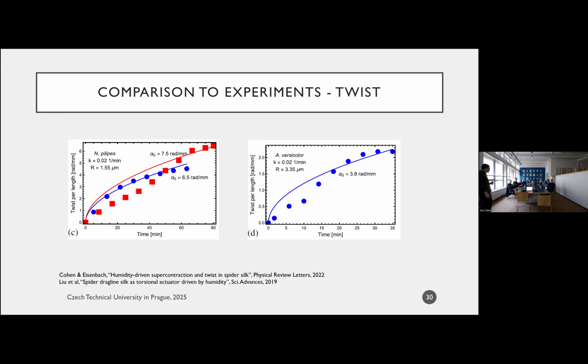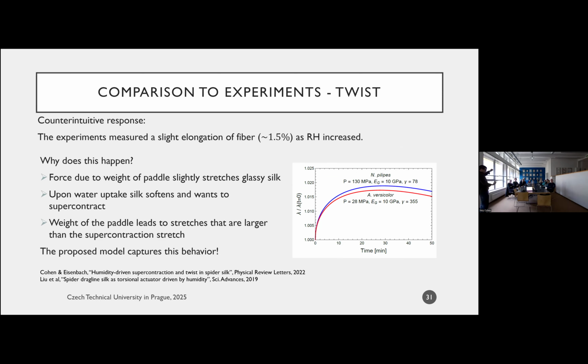And then the reviewer asked us, he said, in the experiments, it turns out that the people who conducted the experiments always also measured an elongation of the fiber, right? So the fiber itself, they had this silk fiber, there was a paddle on it, and it turns out that as the water diffuses into the fiber, we would expect it to supercontract, but it didn't supercontract. It elongated by about 1.5%. And so that forced us to think a little bit. Why is it stretching, right? It shouldn't be stretching.